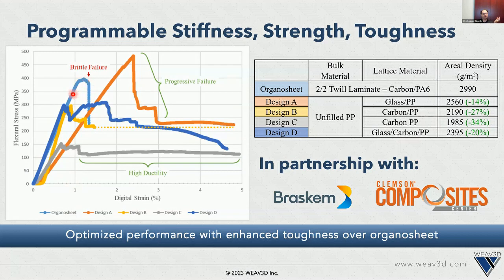If you look at this light blue line here, the organosheet has a very good modulus and a fairly high yield strength. But once it yields, it fails basically catastrophically in a brittle failure mode. So it has no additional energy absorbing capacity after that first failure.